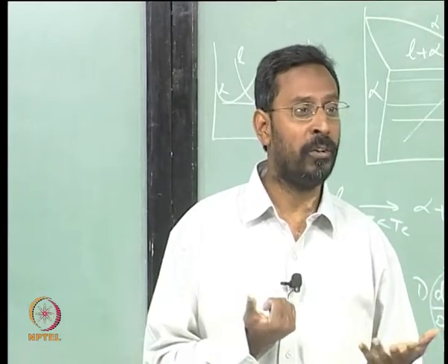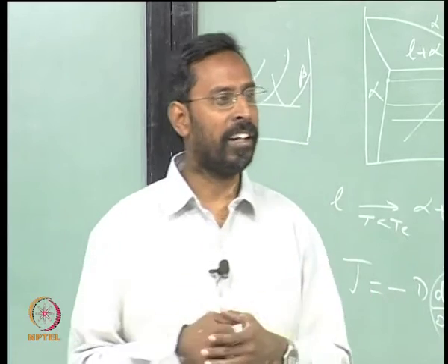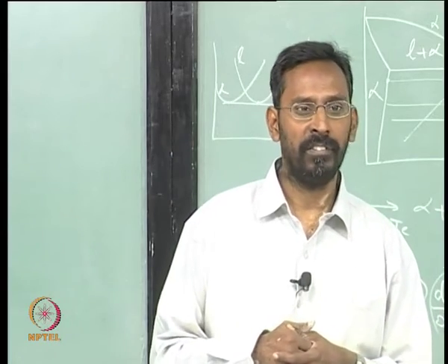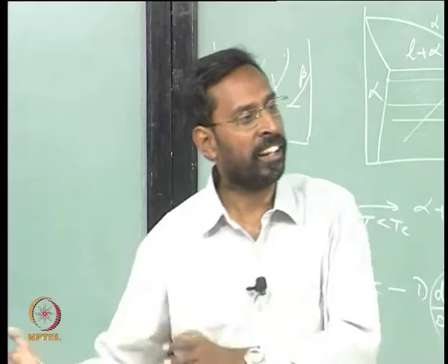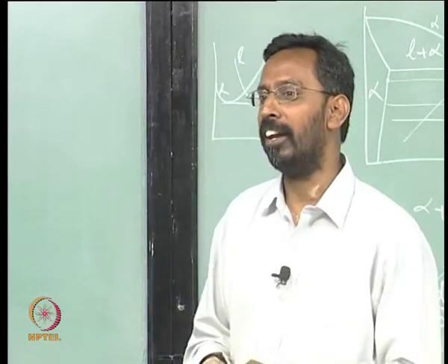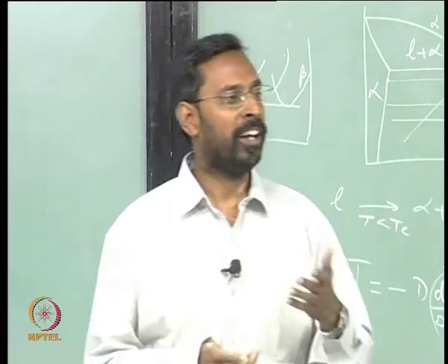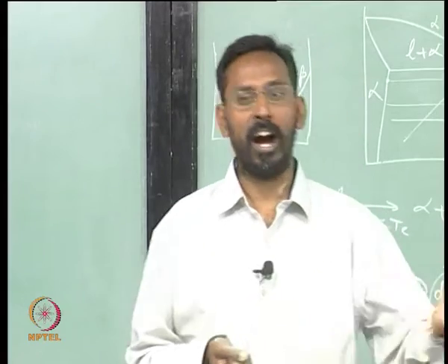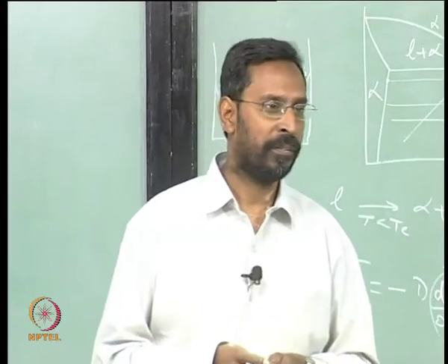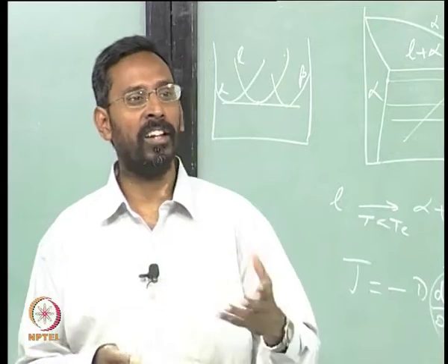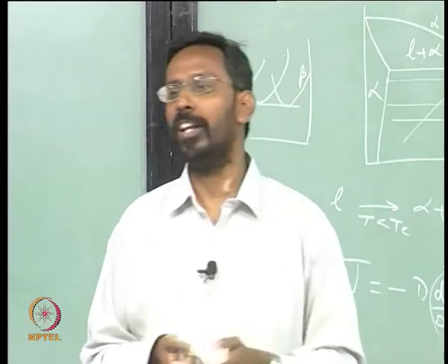And where do you see that eutectic? You see that eutectic only in white cast iron, you do not see it in any other cast iron - whether grey cast iron or nodular cast iron, you see graphite there, which is not a gamma plus cementite eutectic. Gamma plus cementite eutectic, called ledeburite, is seen only in white cast iron.